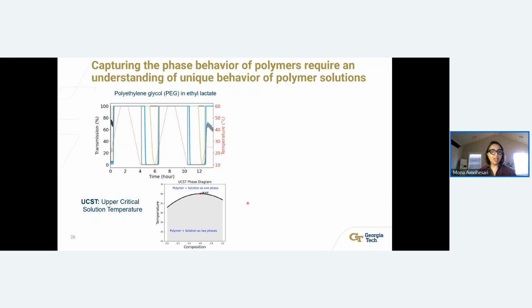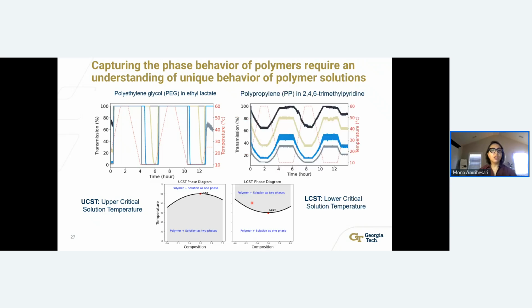But is this the only behavior that we see in polymer solutions? No, we also have a polymer like polypropylene in 2,4,6-trimethylpyridine, an example that has LCST behavior, meaning that the polymers get dissolved and the transmissivity goes up at the lower temperature, and at higher temperature, the transmissivity drops to a lower value. But this is not the end of the story. Some of these polymers have both UCST and LCST behavior in the same solvent, which makes it very challenging to standardize a method that can capture all these changes in the polymer solution.